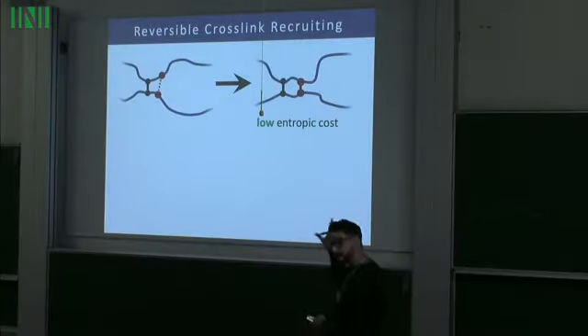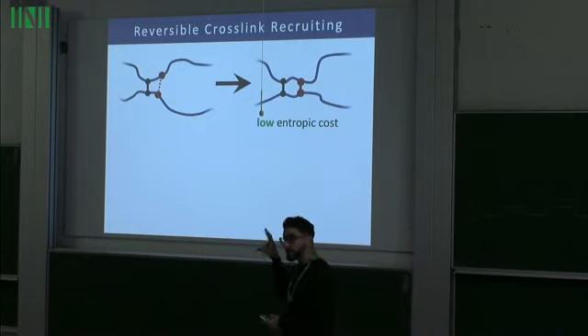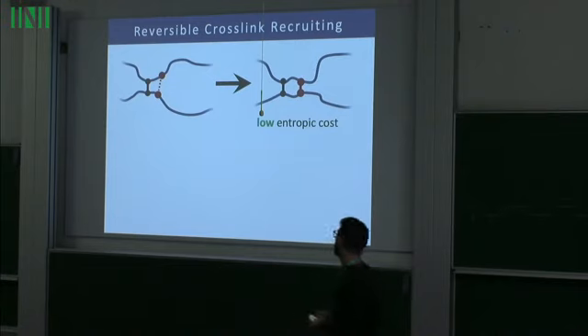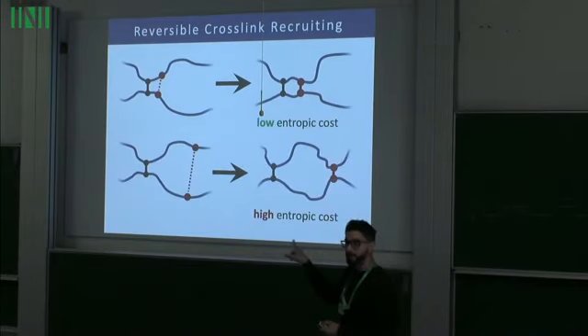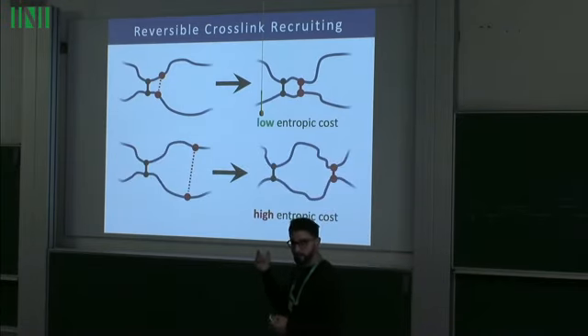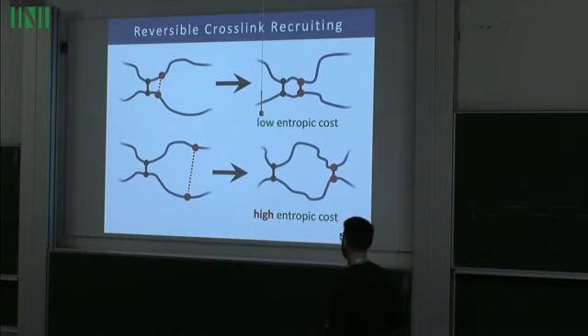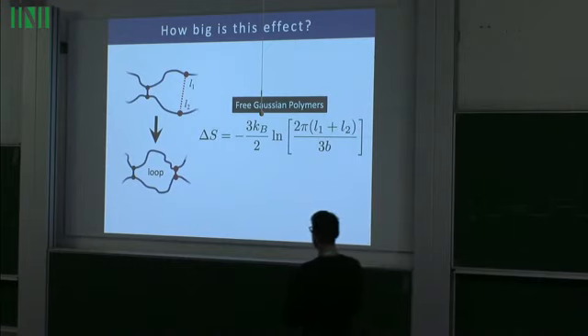Okay? So the entropic cost for that bond is very low from the perspective of the polymer chains. Okay? So I don't lose much entropy. If I make that bond further away from the permanent crosslink, now I cost quite a bit more entropy. Okay? And so indeed, there's this built-in equilibrium thermodynamic bias for the reversible crosslinks to cluster near the permanent crosslinks just by entropy. Okay? And so how big is this effect?